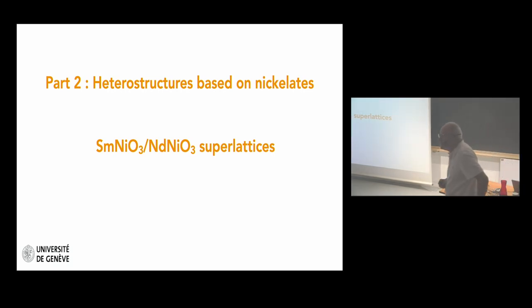Yes? I see what you mean. Yes, but in fact, the U in the system is fixed. And what happens is that the transition will take place for a certain gain in energy delta S, which itself is linked to the breathing mode. So it's a very nonlinear relation. When you change slightly the size of the octahedra, you change quite dramatically your transfer of electrons.